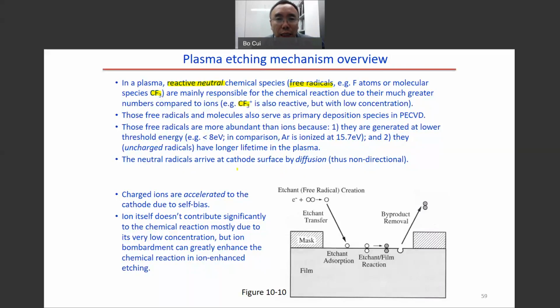On the other hand, because the free radicals are neutral, they come to the surface by a diffusion process, so they are not directional. On the contrary, we know the ion will be accelerated to bombard the surface. So even though the ion does not help the chemical etching too much, it can contribute to the anisotropic etching process.